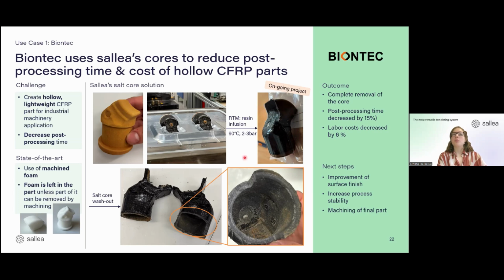Now, an opening has been made to wash out the core. And this is how it looked in the end. So we managed to remove most of the core. And here is even a zoom in of the core inside. What was really good is we could greatly remove the core. However, you see that there is still some of the salt of the core left on the surface. However, that can also be machined away if needed. It showed that we could have a complete removal of the core.